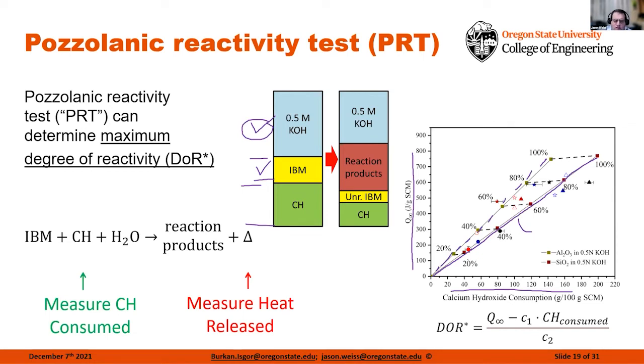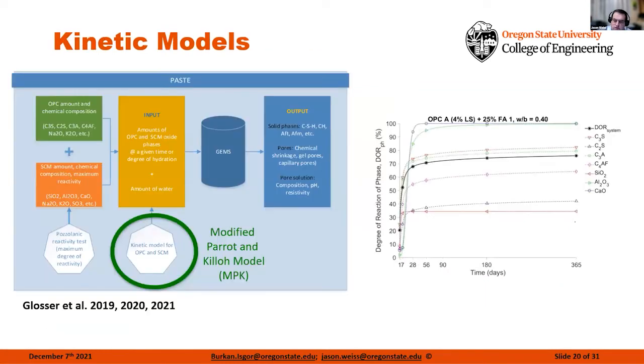So now all of a sudden, if we start to plot our data, we can say, well, these points start to fall into this range of about 20 to 30% reactivity, where something like a silica fume up here may be around 80% reactivity. So all of a sudden, we can remove arbitrary assignments of how reactive these materials are and really get things that are fundamentally based on the chemistry and the amorphous nature of these materials.